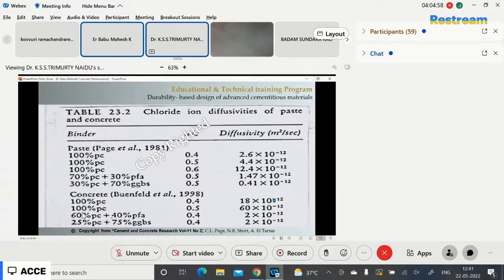So this slide speaks about the chloride diffusivity of cement paste and concrete with various binder systems and varying water cement ratios. For ordinary Portland cement with a 0.4 water cement ratio, the diffusivity is 2.6, with 0.5 it is 4.4, and with 0.6 the diffusivity of chloride ions is 12.4. If you take blended cement with a 30% replacement of Portland cement by fly ash at a 0.5 water cement ratio, it is 1.47. This is a huge variation between ordinary Portland cement and blended cement.